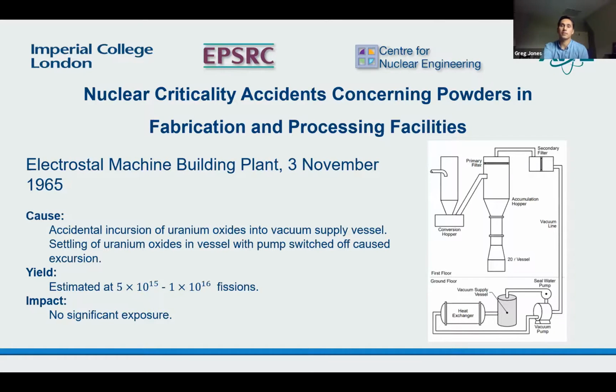And this meant that when the vacuum supply was switched on, a large amount of uranium oxide slurry entered the vacuum system, building up large volumes, specifically in the vacuum supply vessel that you can see in gray at the bottom of the image. So interestingly, this only actually resulted in a criticality excursion when the vacuum was switched off, because it caused the uranium oxide to sediment to the bottom of the vacuum supply vessel.